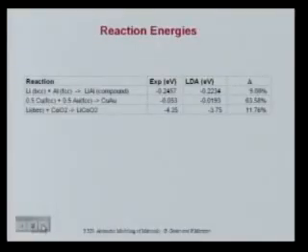I sort of want to end with showing you some reaction energies very quickly, and I'm going to make it systematically harder. So here's a simple one. A metal, lithium, BCC, with another metal, aluminum, forming a lithium-aluminum compound. Here's the experimental reaction energy. Here's the LDA one, 10% off. That's classic. Metallic reaction energies, you're somewhere in the range of 5 to 15%.